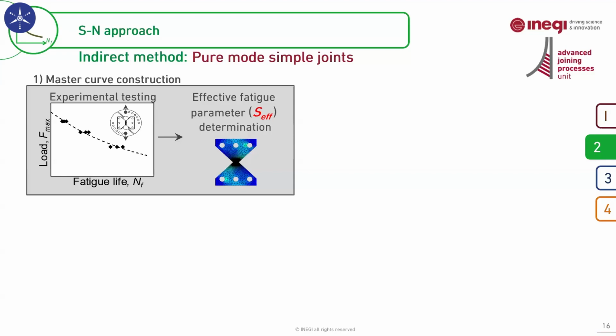And as I mentioned before, the most important challenge in the indirect methodology is to select or develop an equivalent fatigue parameter or stress parameter that can take into account the effect of all the important factors that change the fatigue life of that adhesive.